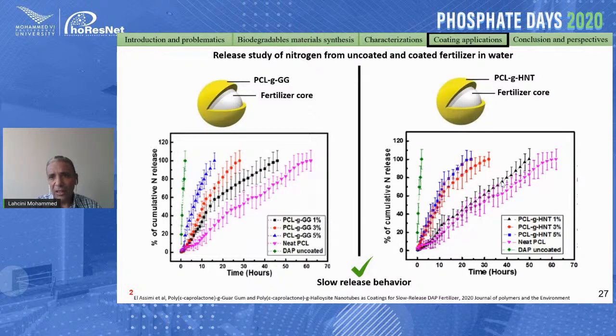This is a good thing, but we observed that when we increase the fillers, the release is a little bit faster than with the neat polymer. This is maybe because of the hydrophilic character of the fillers, or maybe because of the low molecular weight of the polymer. We are now investigating the effect of molecular weight on release, and also studying whether the crystallinity of the polymer affects the release. We are also making some cross-linking to have a more stable polymer.